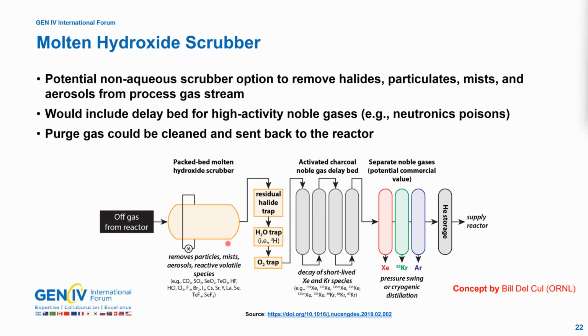And this initial scrub can be used to remove things like particles, mists, aerosols, and it can actually be used to neutralize reactive volatile species, including things like some of the halide gases. Any halides that get through could be captured in a residual halide trap. Then you've got your water trap for any residual water that does come through. You've got your oxygen trap.